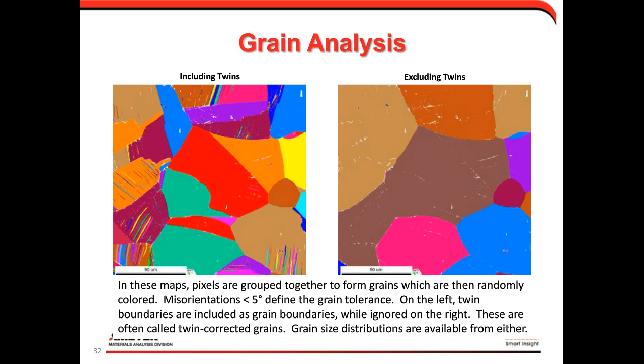So we go pixel by pixel in the measurements and say if the misorientation between those 2 pixels is less than 5 degrees, it's going to be within the same grain. And if it's greater than 5 degrees, then it's going to be a different grain. And so as we repeat that process for the whole measurement grid on the left, we determine the grains, and then we just randomly color these to show the size and morphology of the structure. So you can see, we see the grain structure, and we see a number of the fine lamella twins in a number of the grains.